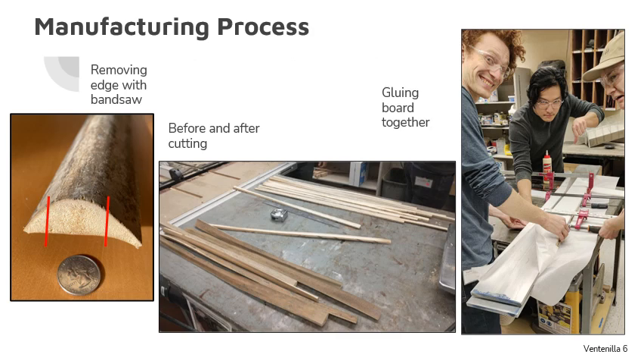All right. Before we could get to doing the actual material testing, our team first had to process the raw palm fronds that were shipped in from Florida in order to make boards. The process that we developed that worked the best was to first remove the sharp edges on the sides of the fronds using a bandsaw, as indicated by the red lines on that image. In the image in the middle, you can see the now cut palm fronds that have been then run through a planer to create two flat surfaces.